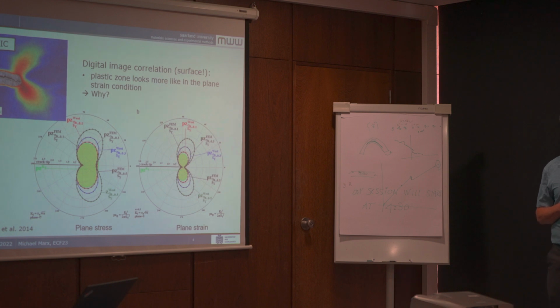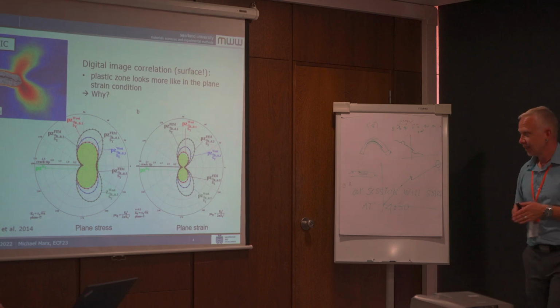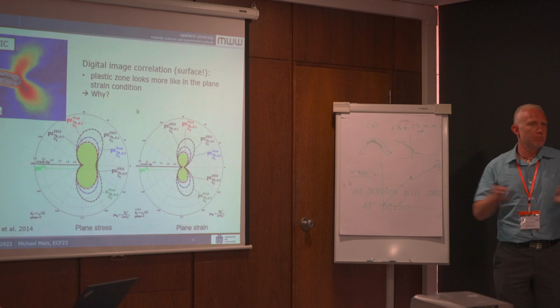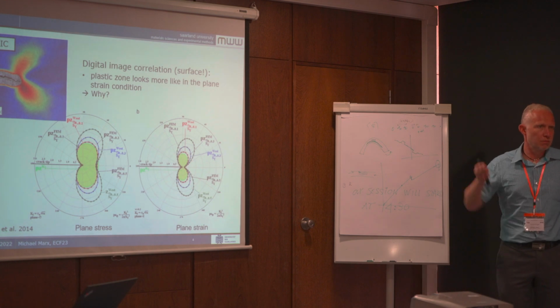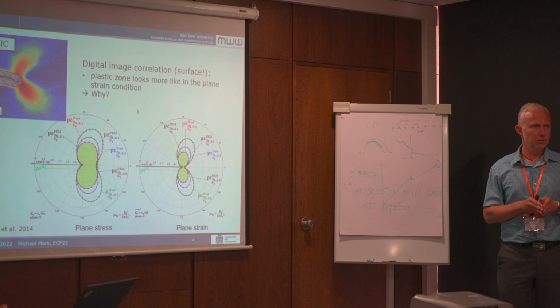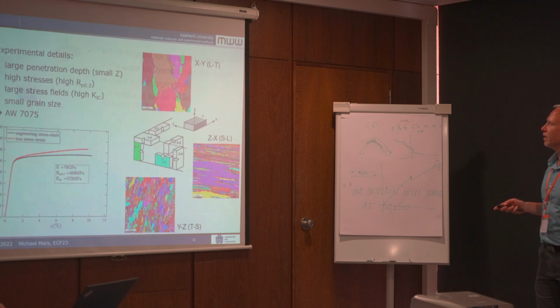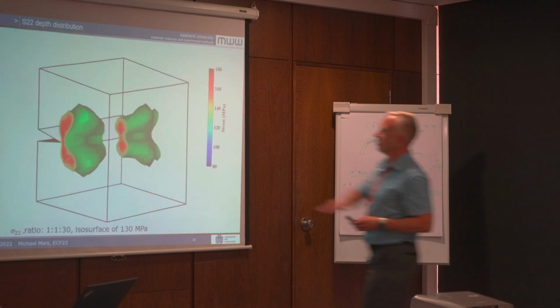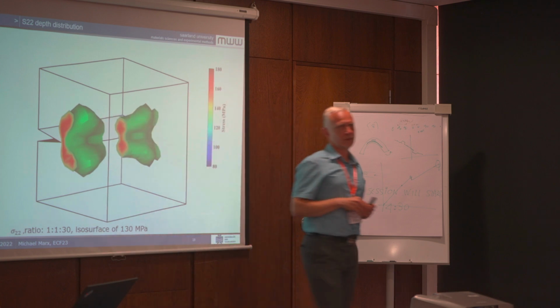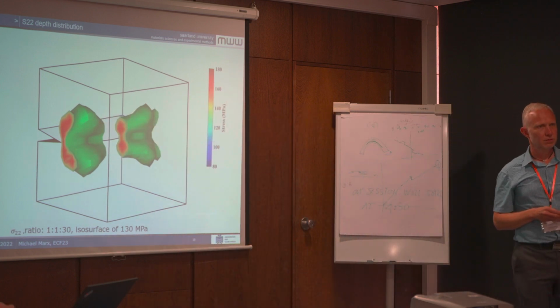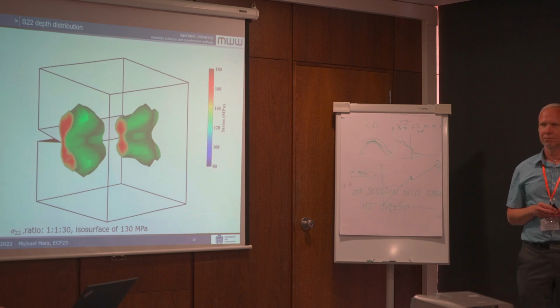So, yeah. Maybe just a small remark. In the middle plane, you're not in plane strain. You really need a very thick specimen to have plane strain at the center. Yeah, but we could not get more information, even if the specimen would be thicker. Because if it's relatively thin, which I guess it is in your case, it's not plane strain in the middle. Yeah, but it's nearly there. Yeah, I mean you get this effect. Okay, thank you. Sorry.